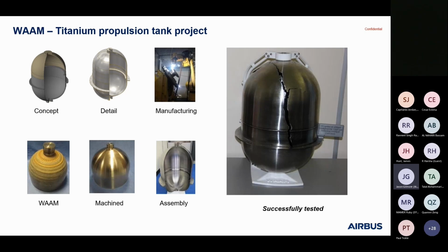Nuclear AMRC did a great job on machining. The Welding Institute welded the two tanks together. So we built two lower shells, two upper shells. We cut a quarter section out of one of them, and then we did a test on the part on the right. This was the only time in my 20 years in Airbus I've been allowed to blow anything up. The test predictions on this one, it would fail between 1,400 and 1,500 psi. So we did a number of pressure cycles before the final burst testing, and this failed at 1,491 psi, so very successful. Some of the doubters said you built it in layers, it will delaminate in those same layers.